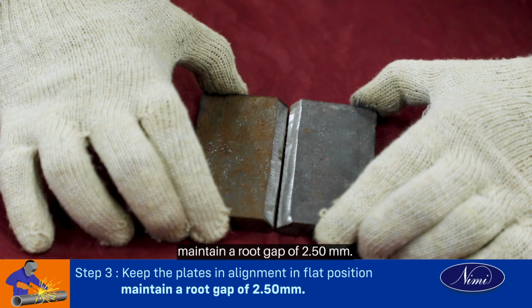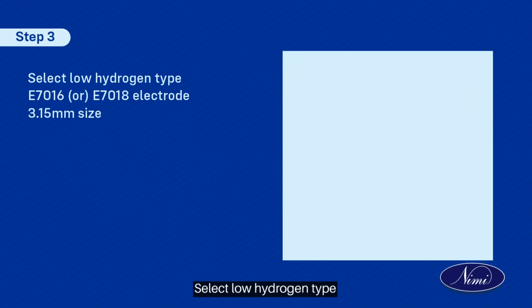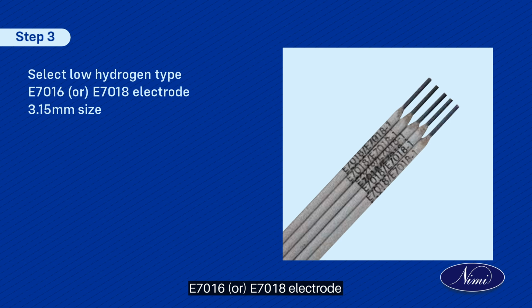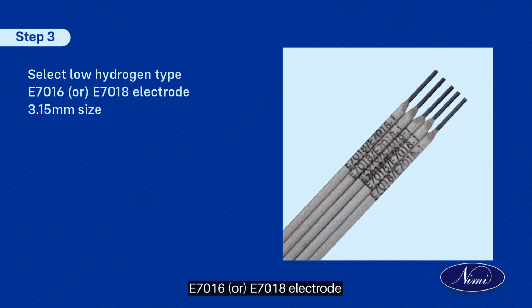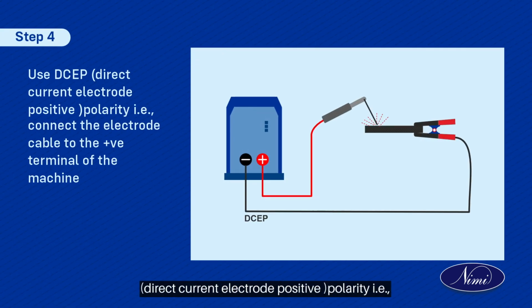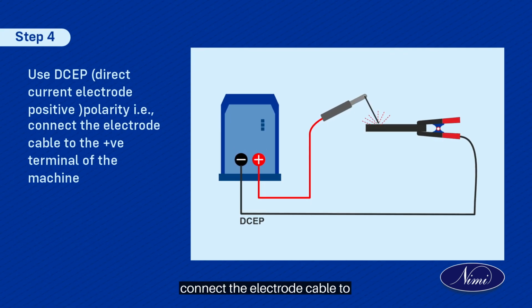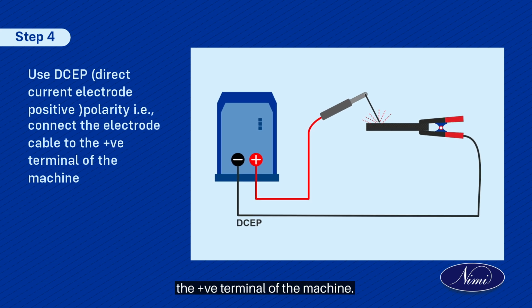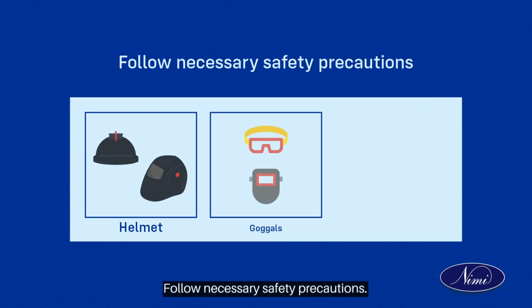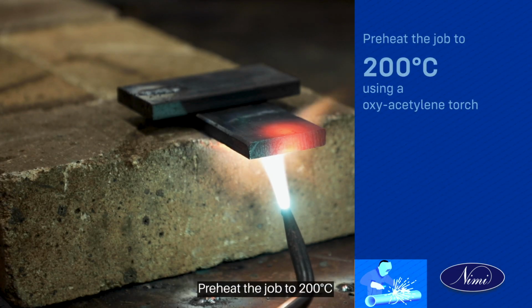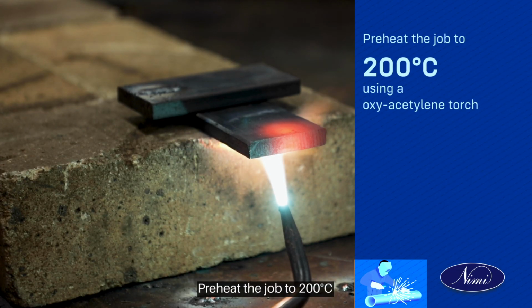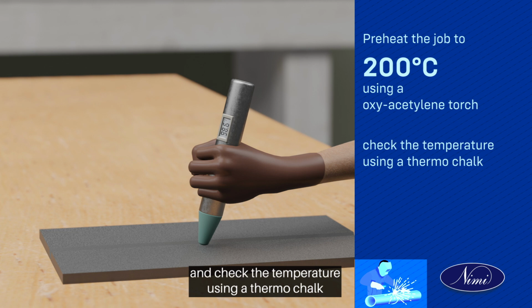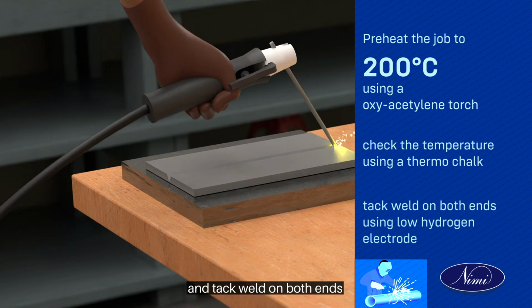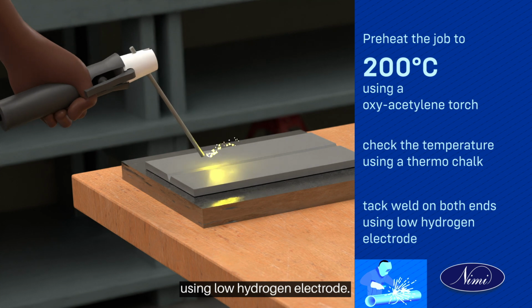Maintain a root gap of 2.50 mm. Step 4. Select low hydrogen type E7016 or E7018 electrode, 3.15 mm size, and use DC EP, direct current electrode positive polarity, that is, connect the electrode cable to the positive terminal of the machine. Step 5. Follow necessary safety precautions. Step 6. Preheat the job to 200 degrees Celsius using an oxyacetylene torch and check the temperature using a thermo chalk and tack weld on both ends using low hydrogen electrode.